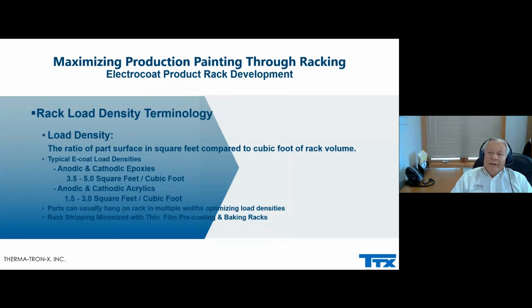Some of the terminology that maybe some of you don't know is what we call rack load densities. In electrocoat rack development, just so everybody understands what it is, and it's also important for liquid and powder, it is the ratio of the part surface in square feet compared to the cubic feet of rack volume. Typical E-coat rack load densities for anodic and cathodic epoxies are 3.5 to 5 square feet per cubic foot. That's the load densities that we see.